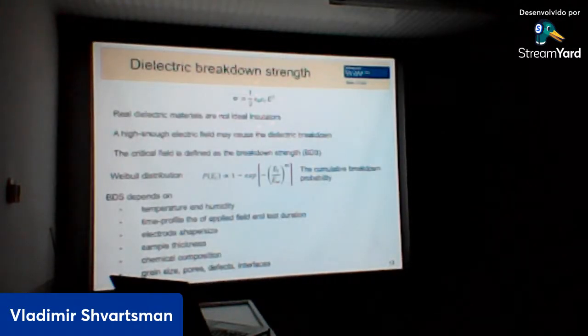Since again we have not only the electric permittivity, we also have the electric field as a parameter which determines the stored energy density. So our materials, to be good for application, have to withstand a high electric field. So they have to have so-called large breakdown strength. This is the critical field at which dielectric breakdown occurs.